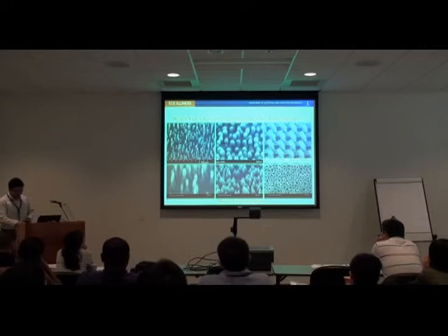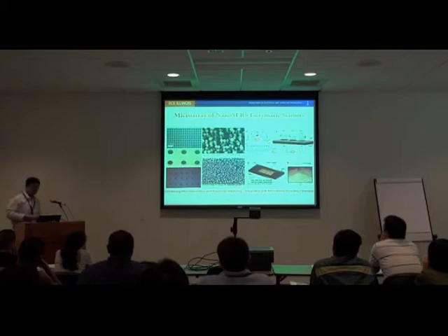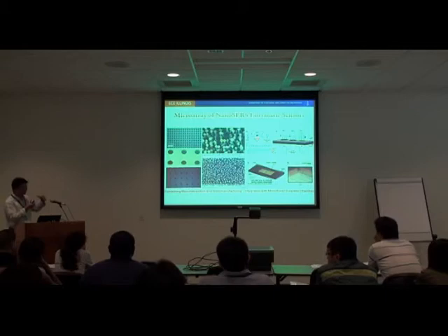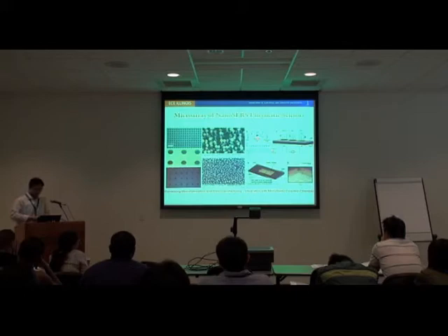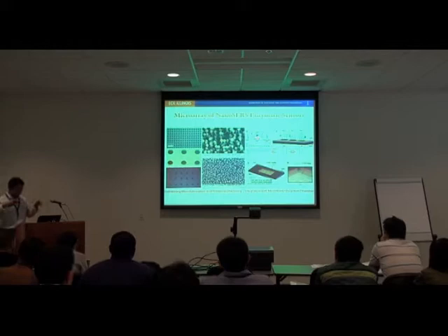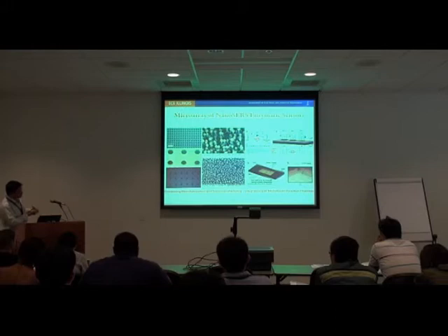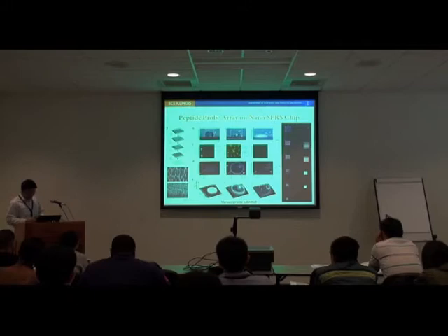Assuming that we have made this surface, we can combine that with optical lithography to make micro dots, micro array patterns. From each dot, we can immobilize different peptide probes. Then we start laser scanning on the surface and get information on the network. This is an example showing that we use liquid sample spotting machines to spot different peptides on different spots over here. Then we assemble them into a microfluidic platform and introduce liquid into this integrated system. The sample we introduce is raw proteins from cell lysate at the very beginning. Then we start the laser scanning to detect the peptide signals before and after the enzyme reacts in this protein in a cell lysate. Here are some examples.